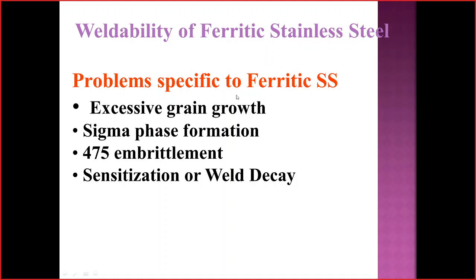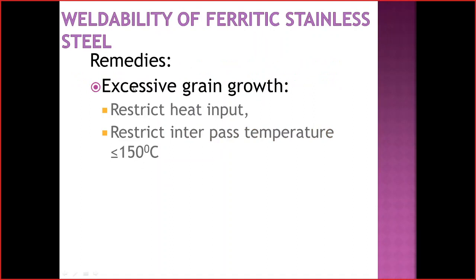Another problem when you use ferritic steel is excessive grain growth. So the grain structure will be disturbed more in the ferritic steel. Sigma phase formation will also be there. Okay, the rest we'll see. To restrict the excessive grain growth, grain growth meaning the atomic structure or molecular bonding in the metal being disturbed, that can be restricted by restricting the heat input. That means we have to provide lesser heat input, on the lower side.